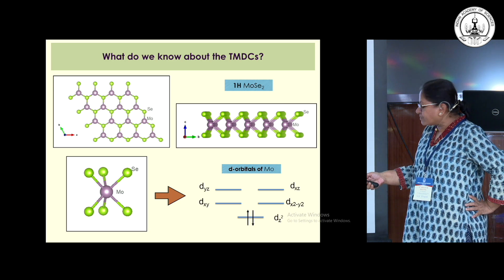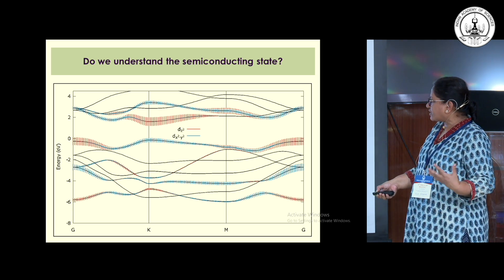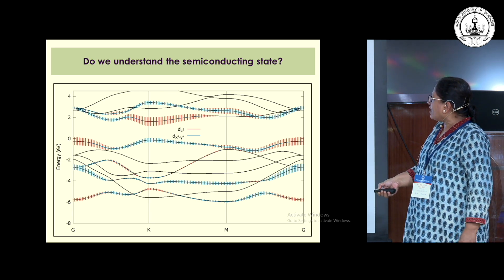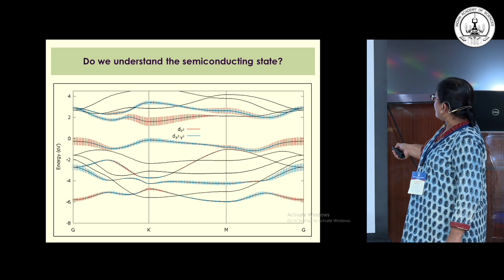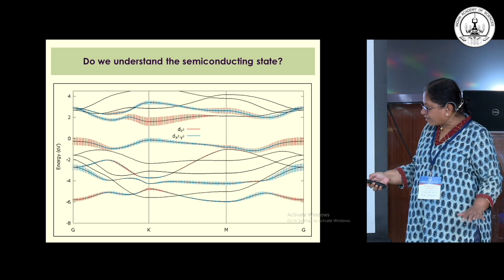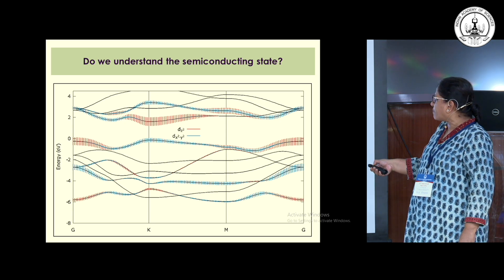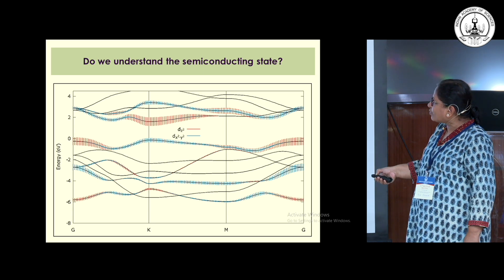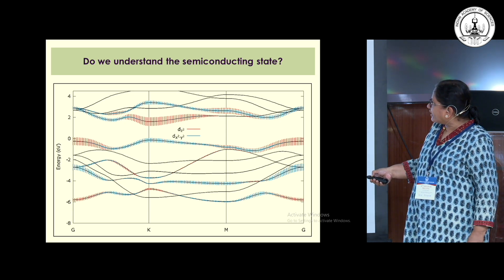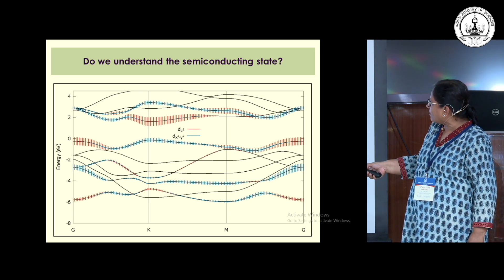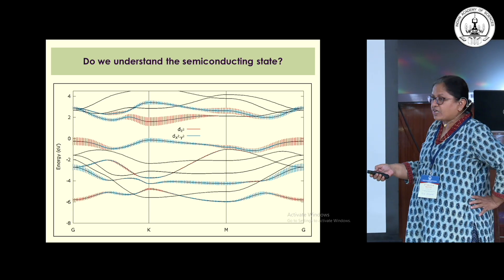If you look at the character and do some simple analysis, what I'm showing are the energies — the band structure plotted along various symmetry directions. These are the highest occupied bands and these are the lowest unoccupied bands. We do get a semiconductor. But we've color-coded the contribution of eigenfunctions to these top bands, taking the dz² and dx²-y² contributions, and you see it's not such a simple picture as previously believed. You have the dz² lower and dx²-y² higher in some regions, and an exact reversal elsewhere, yet you still have the semiconducting nature.